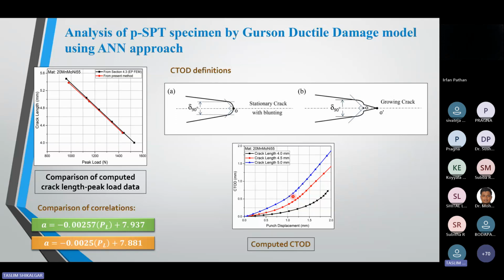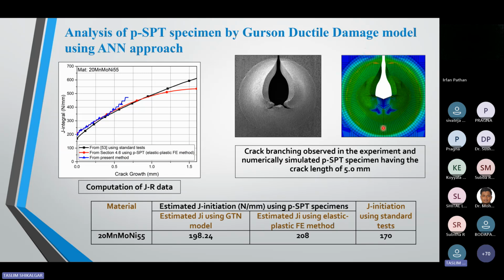So here you can see my numerical simulations. I observed that my crack started growing, and after a few growth steps I observed crack branching, meaning the crack is going in two different directions. So I wanted to verify whether this is possible in the experiment.